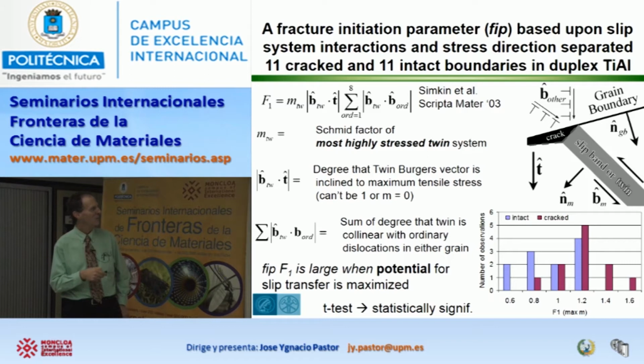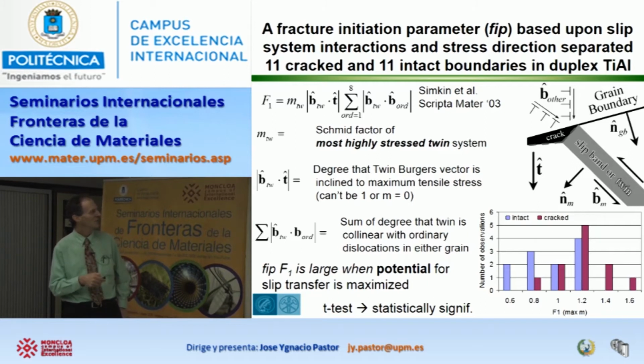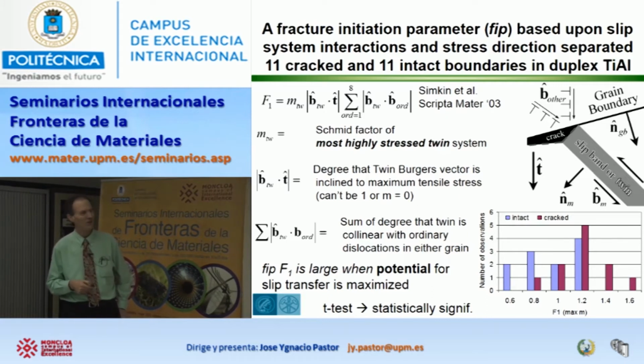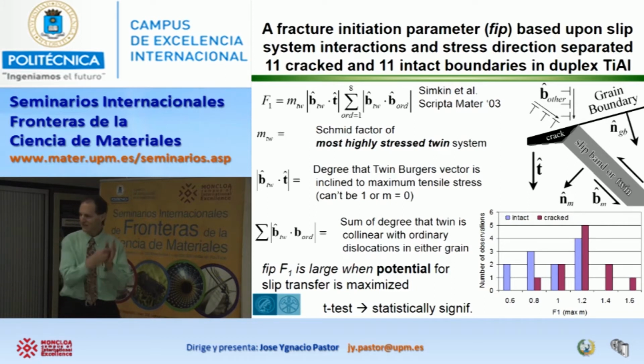If I have a high probability Schmid factor right here of a twin happening, such as this, and if the Burgers vector of this twin is lined up more or less with the tensile axis, or at least in that direction, and if I have the ability to get dislocations on the other side to line up with this twinning shear direction, then maybe I can get the conditions that would lead to a crack. So that's basically what this is about. So if I look at intact boundaries and cracked boundaries, I see that I get a difference in the value of this parameter right here. So this is like a probability statement. The higher probability, the larger it is. So it's not a complete separation of two populations, but it is statistically significant.